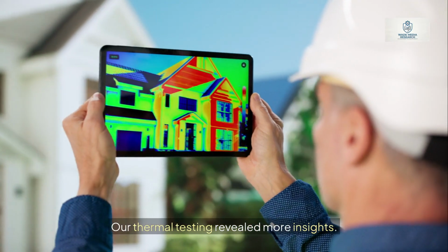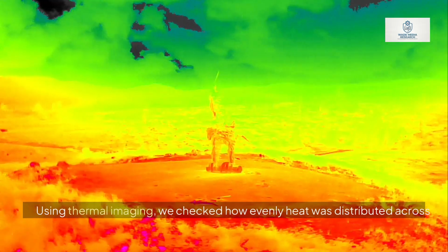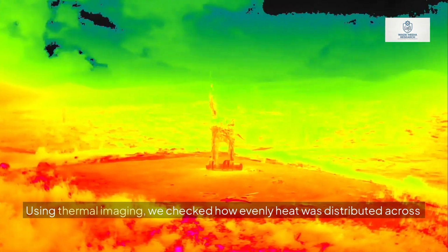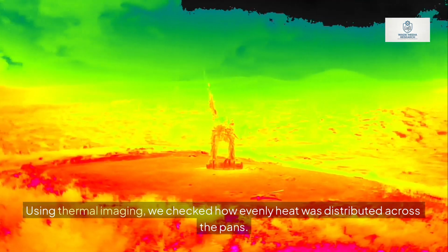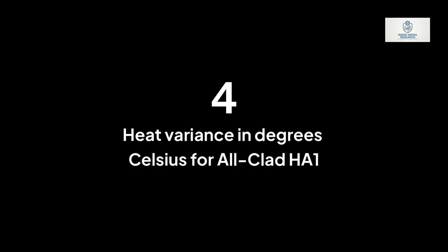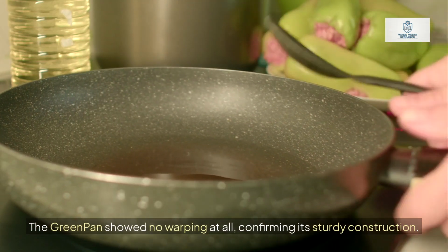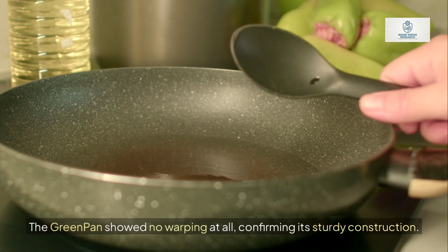Our thermal testing revealed more insights. Using thermal imaging, we checked how evenly heat was distributed across the pans. The All-Clad HA1 exhibited a heat variance of just 4 degrees Celsius, while the Hex-Clad showed a wider variance of 8 degrees due to different materials. The Green Pan showed no warping at all, confirming its sturdy construction.